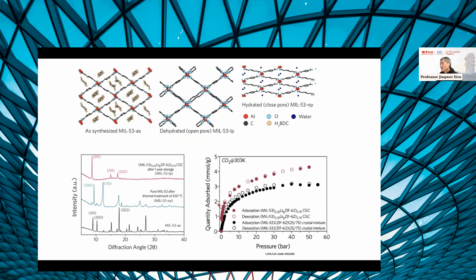But how can we do that? By compositing the crystal MOF with glass, we can use the high temperature MOF glass as a super glue to freeze the large pore phase of the MOF. It's a very long sentence, but long story short, we can freeze the large pore phase within the glass, making the composite glass much more porous compared with either of the parental phases, because one of the parental phases will become a kind of small pore phase in this case. So that's a very exciting discovery for us.